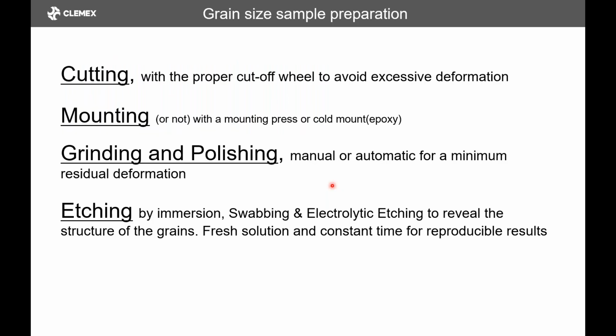So before we get into the measurement, we should have a quick look at the sample preparation, because it's quite important. If we don't want to distort the grains, we need to make sure that the material will not be deformed. So when we cut the original sample, we need to have a proper cutoff wheel so we avoid excessive deformation. The mounting is important, but not necessarily. Sometimes you could work with an unmounted sample and still, of course, get some grain size. Grinding and polishing is the next step. Now, what's important here is that we have to end up with a good sample preparation, and the reason is not just to have a nice final finish, but also to remove any residual deformation by having some organized steps for material removal.